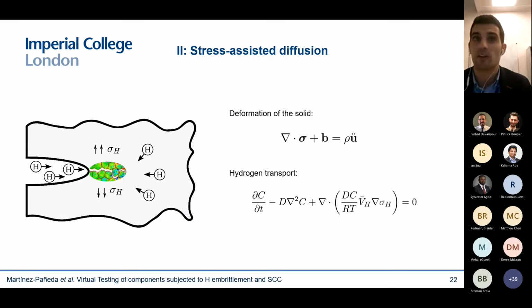So that takes me to the second ingredient, the chemistry. We want to be able to capture how much hydrogen we have, where and when, as I said before. So we solve 2 problems. One is the deformation of the solid. This is the standard balance of linear momentum. And then we solve an equation for the transport of hydrogen. So hydrogen is traveling within the metal according to this, which is an extended version of Fick's law. And you can see the coupling with the mechanical problem very clearly here, right? So there's the gradient of this hydrostatic stress here.